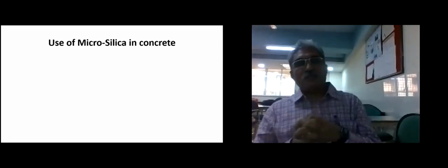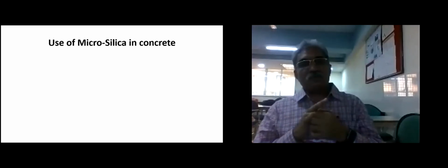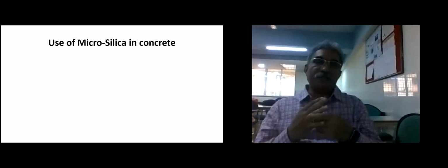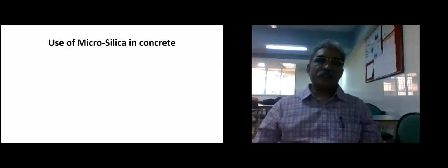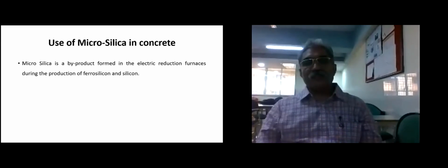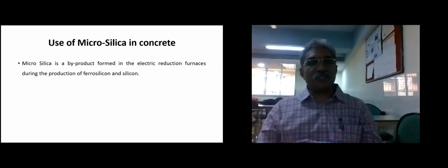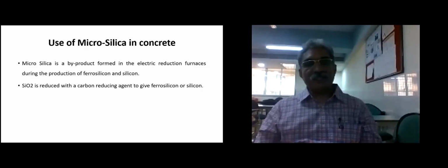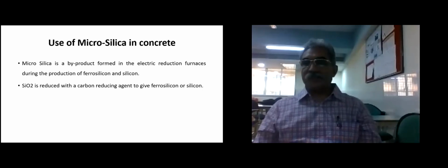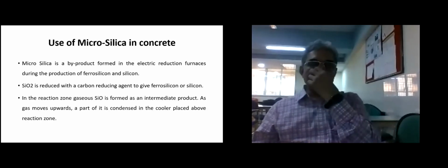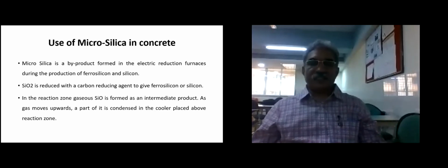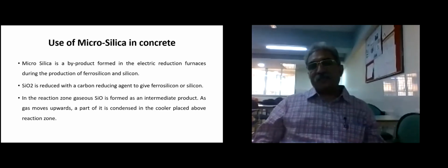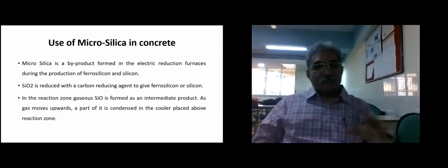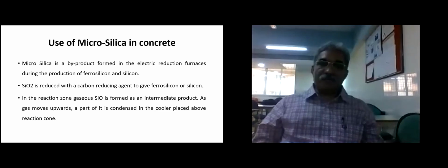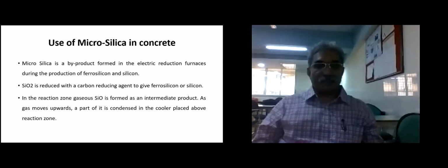Then one of our group, well, along with me, we have tried this microsilica in concrete, and microsilica is a byproduct formed in an electric reduction furnace during the production of ferrosilicon and silicon. The SiO2 is reduced with a carbon reducing agent to give ferrosilicon or silicon. In the reaction zone, gaseous SiO is formed as an intermediate product. As the gas moves upward, a part of it is condensed in a cooler placed above the reaction zone.